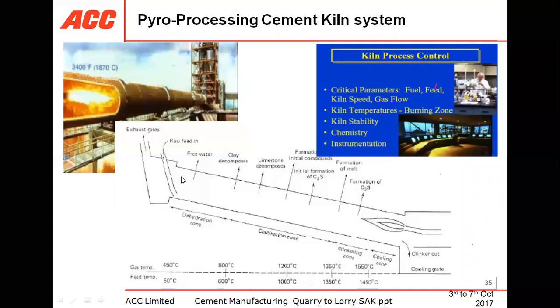First, in the dehydration zone it becomes moisture free, then decomposition starts around 400 to 600, and at a temperature of 800 complete dehydration happens. Then as this material moves further, it goes to the calcination zone, where calcium carbonate present in limestone becomes calcium oxide and starts to combine with silica present in limestone and other raw materials to form calcium silicate bonding. This process takes place in the zone around 1200 to 1300 degrees. Then finally, as it moves to further temperature zones like 1350, 1400, 1500, actual clinker starts being produced.